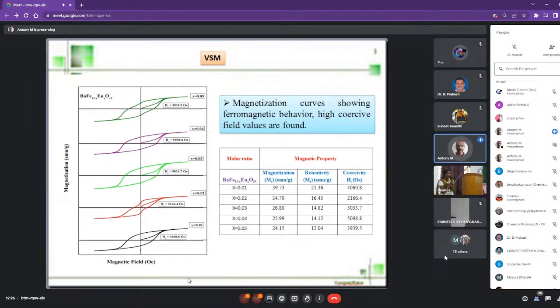This was my VSM result. The hysteresis loop tells the source of ferromagnetic behavior, and the coercivity values are found by changing the ratios. By increasing the ratio values, the magnetization and the retentivity values decrease gradually. The highest coercivity value occurs when the ratio x equals 0.04.